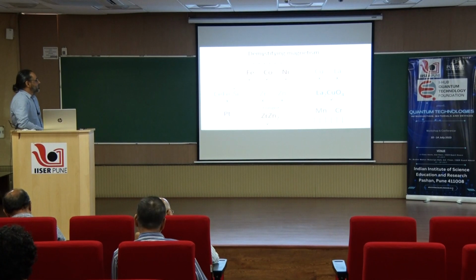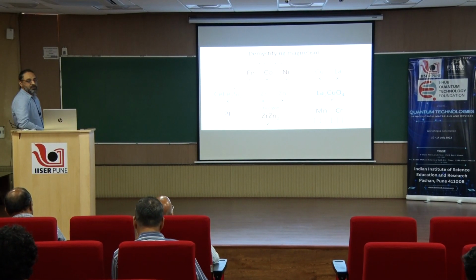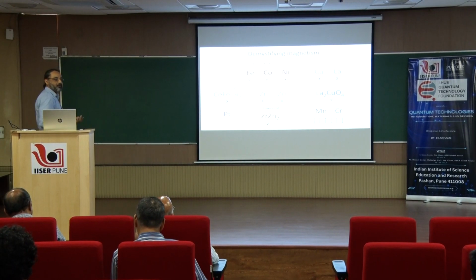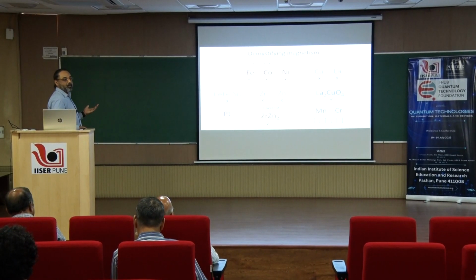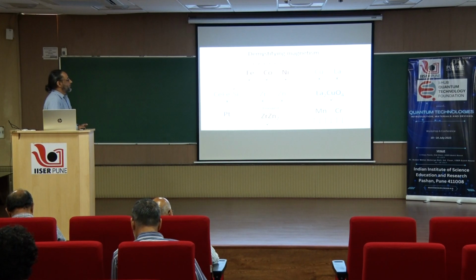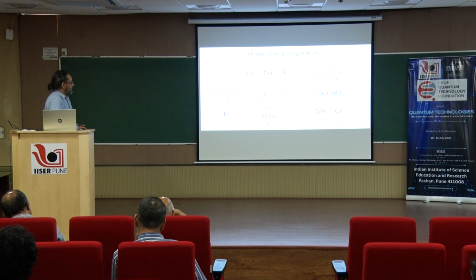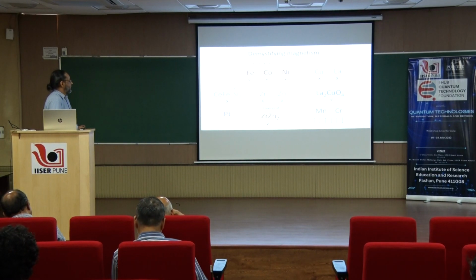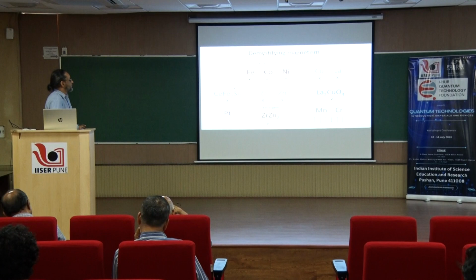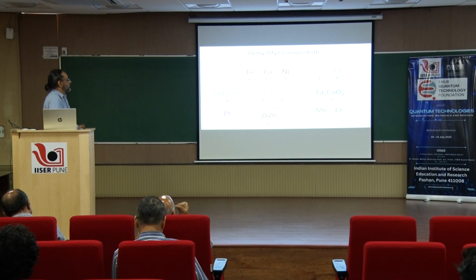On the other hand, on this side you have copper, a piece of copper does not get attracted to a magnet because it is not a ferromagnet, it is also not an antiferromagnet, but there are compounds of copper which you saw in the previous presentation, where copper exhibits a magnetic moment. And then of course, from the 3D transition metal elements, you have manganese and chromium, which show this antiferromagnetic ordering.